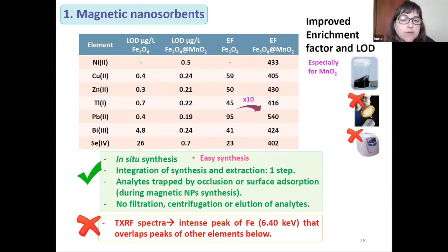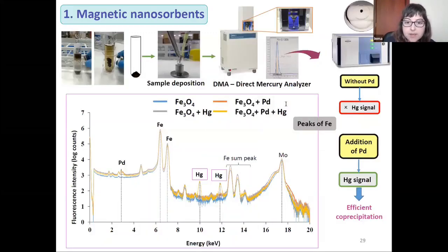Also, we are going to have one drawback, which is the appearance of an intense peak of iron at 6.40 kiloelectron volts and also at double energy, 12.8, that overlaps some peaks, and the elements below these energies cannot be detected. Here in this slide, we can see these peaks of iron that we are going to comment on at the end